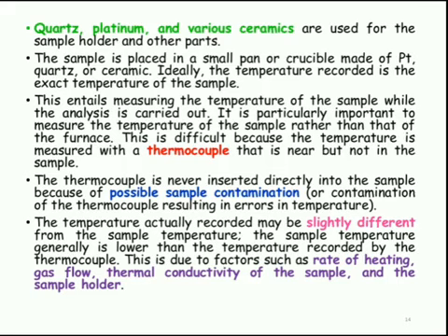This entails measuring the temperature of the sample while the analysis is carried out. It is particularly important to measure the temperature of the sample rather than that of the furnace. This is difficult because the temperature is measured with a thermocouple that is near but not in the sample. The thermocouple is never inserted directly into the sample because of possible contamination of the thermocouple, resulting in errors in temperature. Therefore, the temperature actually recorded may be slightly different from the sample temperature. The sample temperature generally is lower than the temperature recorded by the thermocouple. This is due to factors such as rate of heating, gas flow, and thermal conductivity of the sample and the sample holder.